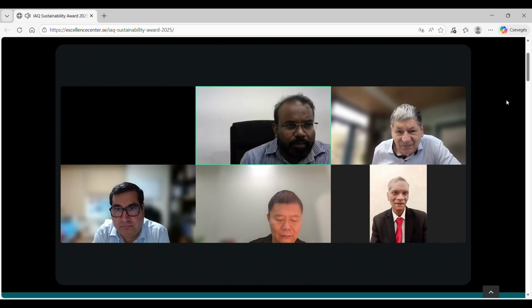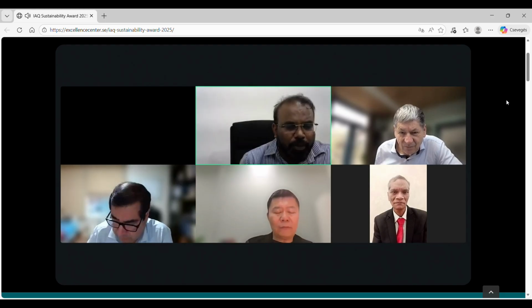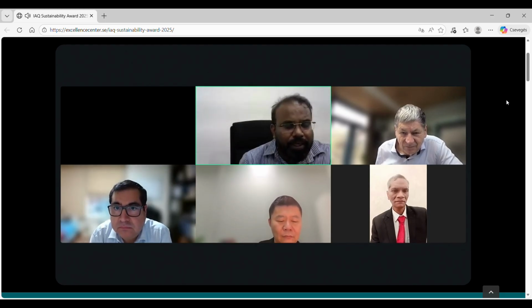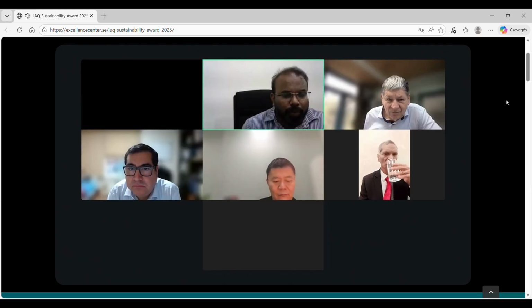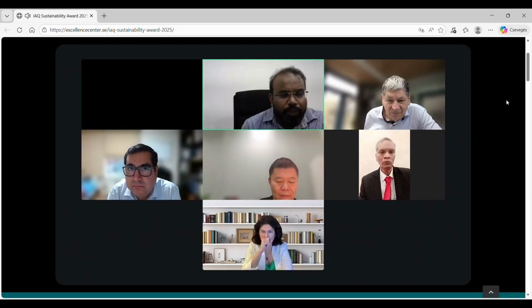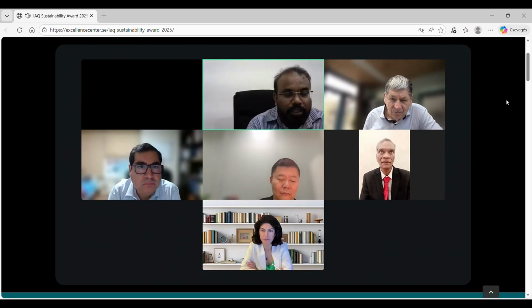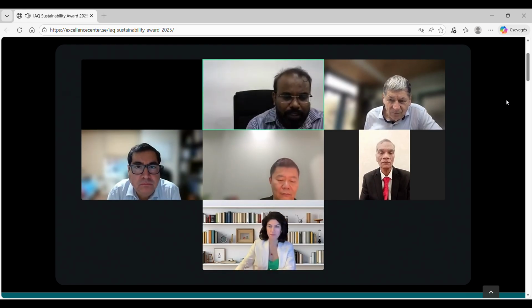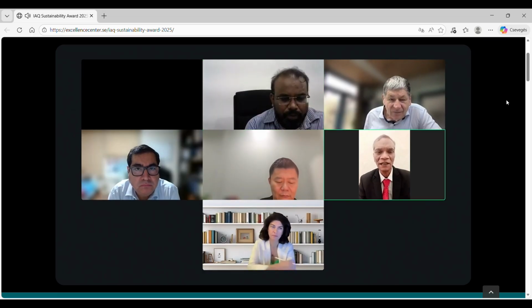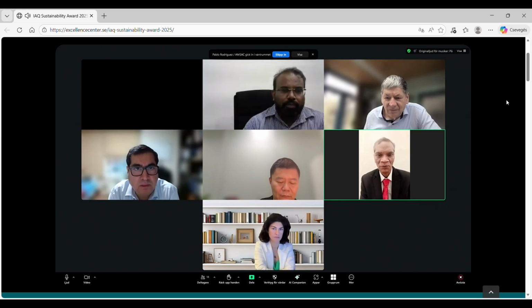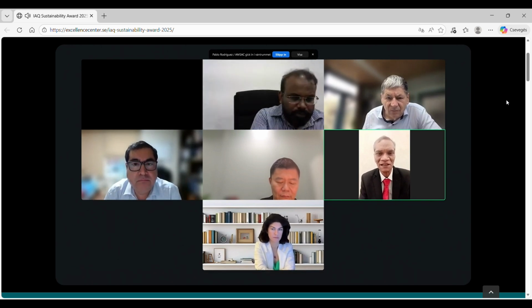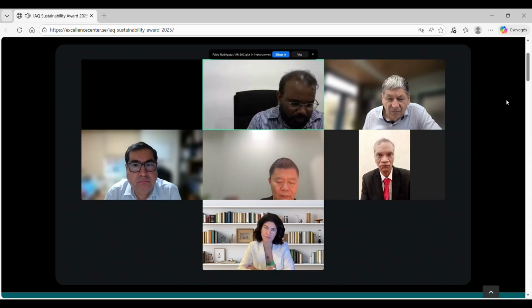Sir, in general, for the sinter plant, the blast furnace requirement will be 9 to 10.5 only. Whenever it increases beyond 10.5, that will not be suitable for blast furnace operation. There they need to add more coke reactions, so direct coke consumption will increase at the blast furnace. So they will restrict it to a maximum of 10.5 only. Okay, let me answer this question if I'm audible. The process capability maximum possible for this process is 0.6, 0.63 to be precise.